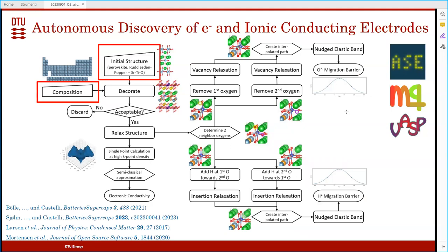In this case, we use a structure prototype. So we take perovskites, both cubic and layered. We decorate them. We calculate the electron conductivity using the Boltzmann equation, and then we look at the conductivities in the oxygen, so we create vacancies. We look at the vacancy mobility of one oxygen, two oxygens. We do the same when we insert protons, and then we get migration barriers both for oxygen and hydrogen, and from that we can try to make them the best possible.